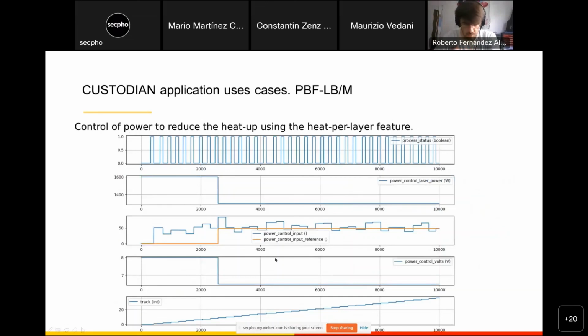What we are doing is defining a reference for the appropriate level of heat during every layer, and we do so by averaging the first layers. We extract the average value of the first layers, and this is defined as the reference for the control after it. Then the controller modifies the power, reducing it to avoid the overheat of the process and enable construction of the part with more stable parameters. This is work that we are currently working on.